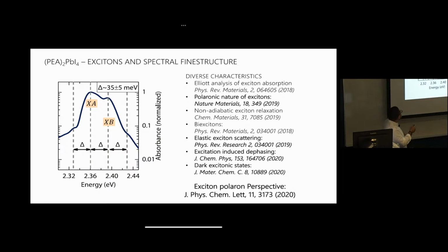Here's your main exciton peak, which for no good reason we're going to call XA. That has nothing to do with any symmetry label; it's just Jack and Jill. XA and XB are the 2 main exciton peaks, so XA will be this main one. But you see another peak here at 35 millielectron volts away. Then there's another one 35 millielectron volts away, at lower energy. So there's this very even spacing.